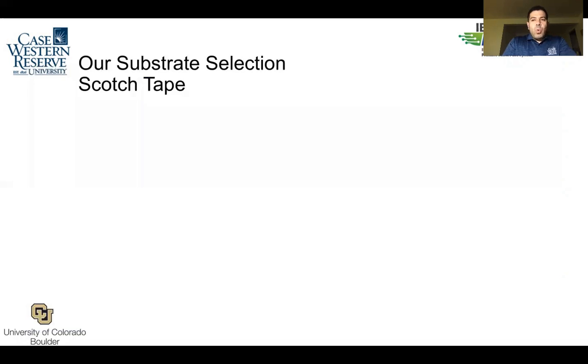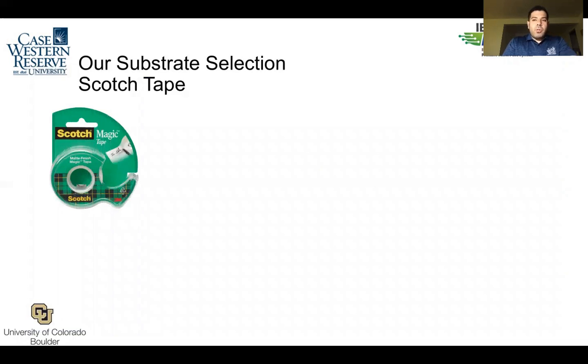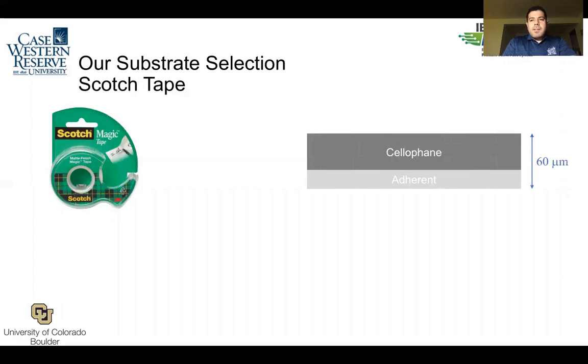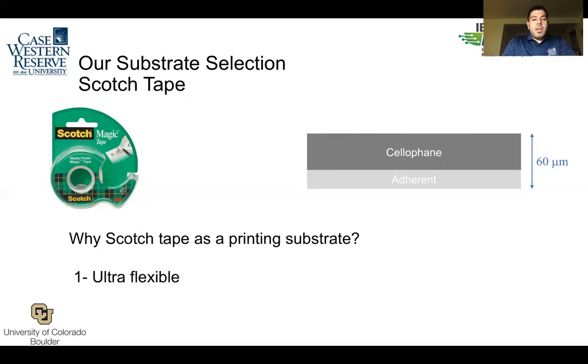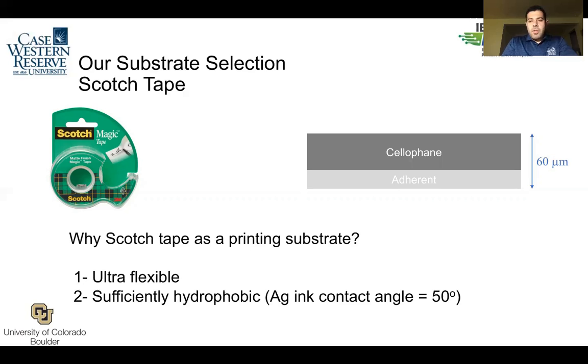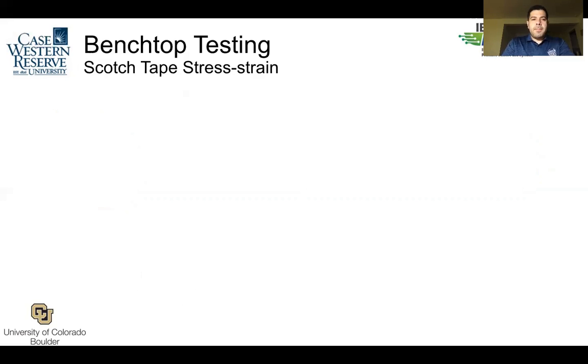Speaking of cellophane, why did we choose cellophane or Scotch tape? Scotch tape is a cellophane material. One adhesive side at the bottom has a thickness of 60 micron. And one advantage of a cellophane tape is it is very flexible and also sufficiently hydrophobic. We tested the silver ink contact angle, which was about 50 degrees, and thirdly it has good printing fidelity. We printed a couple of structures, meandering structures, and they have good printing fidelity.